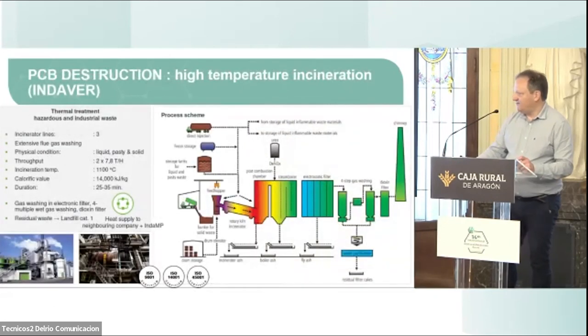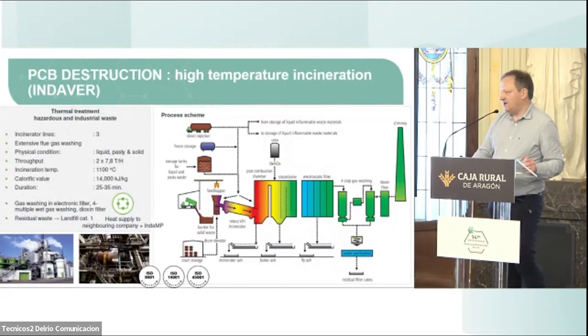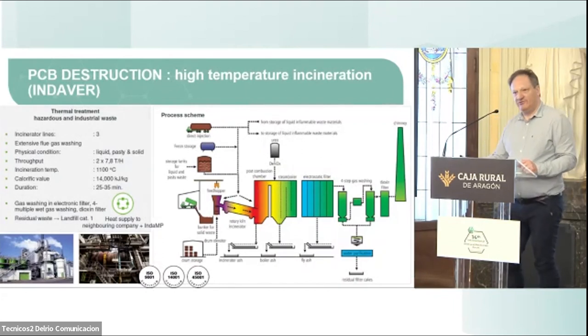This is the incinerator from Indaver. So all the residues containing PCB we send to the incinerator company. I think the most important is the incineration temperature of 1100 degrees and a duration of between 25 and 35 minutes at that temperature to ensure all the PCBs are destroyed.